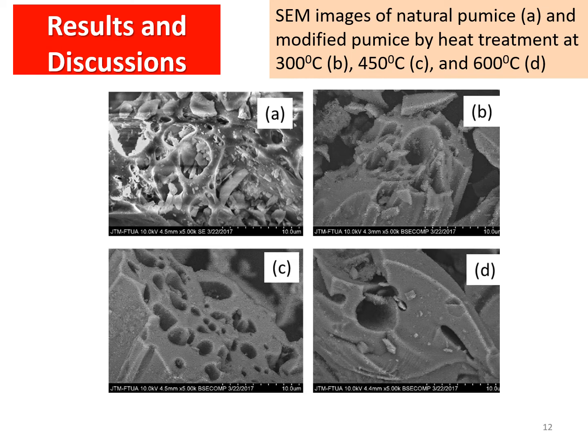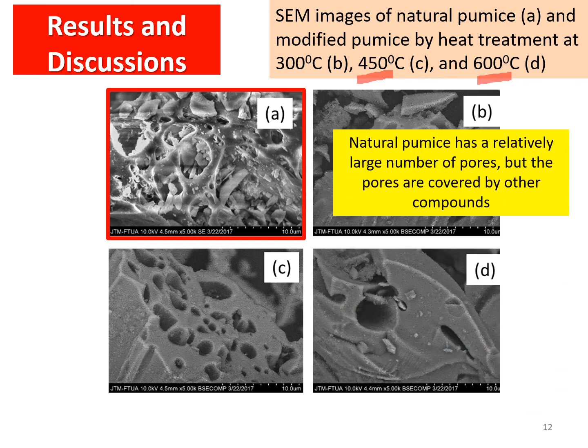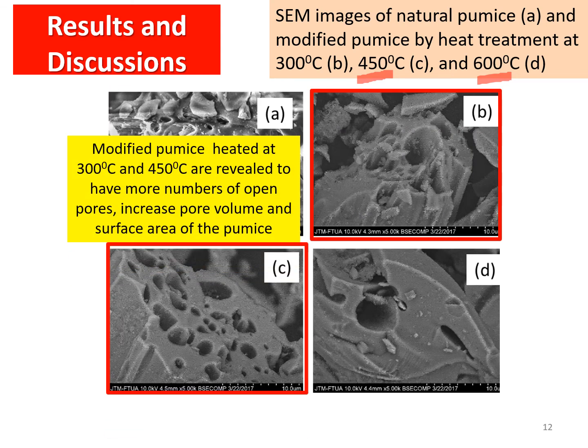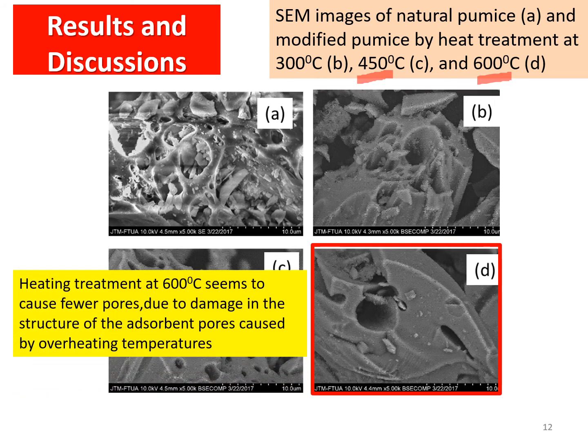These figures show the SEM image of natural pumice and modified pumice by heat treatment at 300 degrees Celsius, 450 degrees Celsius, and 600 degrees Celsius. The natural pumice has a relatively large number of pores, but the pores are covered by other compounds. And modified pumice heated at 300 degrees Celsius and 450 degrees Celsius are revealed to have more open pores and increased pore volume and surface area of the pumice. However, heating treatment at 600 degrees Celsius seems to cause fewer pores due to damage in the structure of the adsorbent pores caused by overheating temperature.